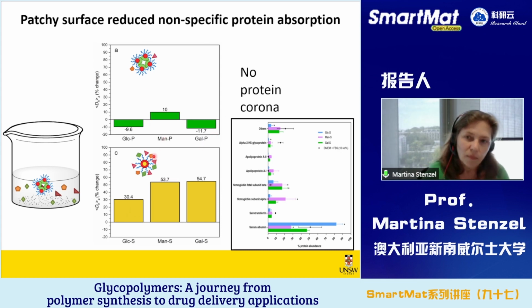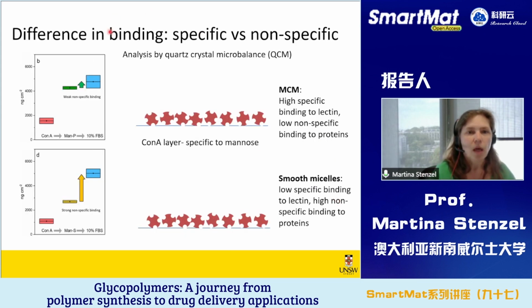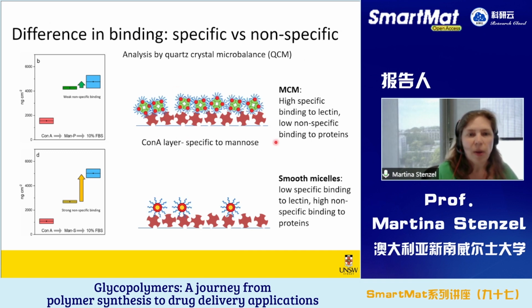So now we can take the protein layer and really identify what's on the surface. This is very important because depending on the type of protein, you get very different outcomes. What we found here is, for example, that depending on the kind of sugar, very different proteins are absorbed. Again, you can quantify the difference in binding using quartz crystal microbalance. What you do here is immobilize a lectin, and then you incubate that layer with nanoparticles. We found the football particles bind very specifically to the lectin, while the round particles did not really bind very specifically. And these football particles did not bind non-specifically to proteins, while the smooth particles did.